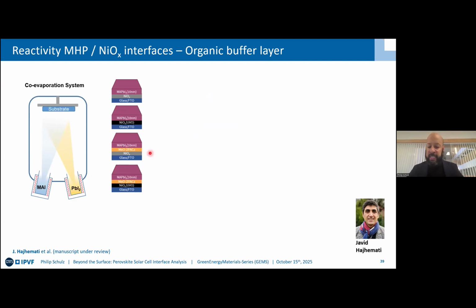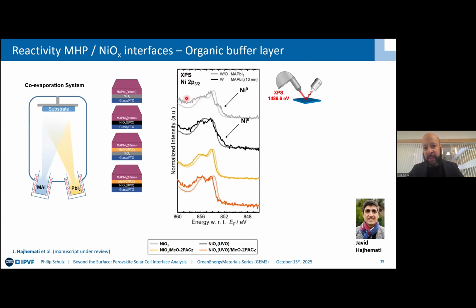We were able to see in XPS that, so I take just this gray curve here on top, if you have just nickel oxide, you can see here the nickel 2p core level indicative of nickel oxide with the hydroxide species. Once you add the MHPs, 10 nanometers on top, and this is now the more noisy, more bold curve, you see the rise of this additional contribution, which is metallic nickel. Now remember, this is also what we saw in the HAXPES measurements, the occurrence of metallic nickel. The UV ozone treatment doesn't stop it, but once you introduce the organic molecules, these contributions really go away, and you now have an interface that does not have this chemical defect.